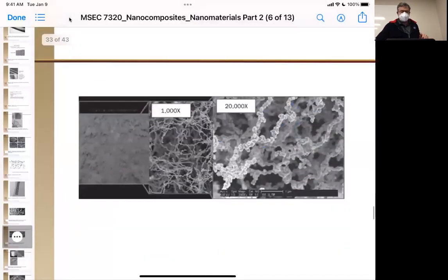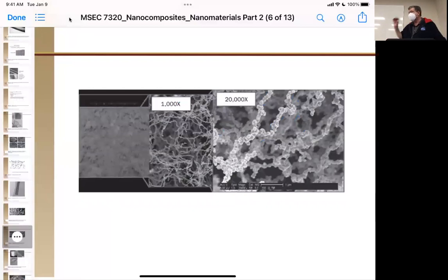So when we move on from that, we can go on to the next one, which is solid metal fibrils. And these are nickel. And you can also do silver, aluminum, other things. Nickel and silver are probably the two most common. Nickel is the most widely used because of its corrosion resistance. Okay, silver oxidizes in air. It also has a certain photoactivity associated with it.